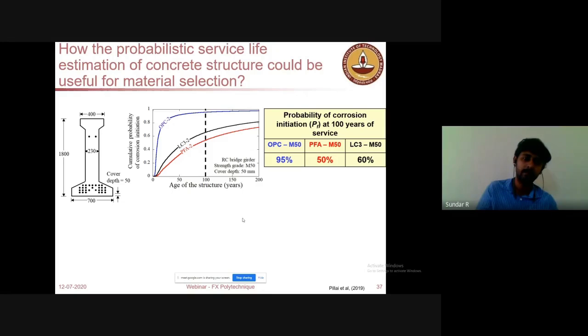We tried 3 different binders, and we saw that under chloride-induced corrosion, the concrete with ordinary Portland cement shows a 95% probability of corrosion initiation at 100 years. So when we want to design a concrete for 100 years with OPC, it is almost impossible when there is chloride.